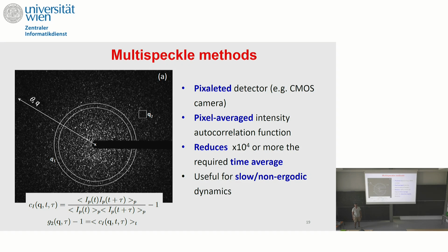If the sample is not isotropic, I cannot. I have to use the trick of a small box, saying the box is small enough such that whatever happens within the Q vectors associated to that box is the same. And I'm just averaging. But I cannot take the ring because things may be different in this direction or that direction.